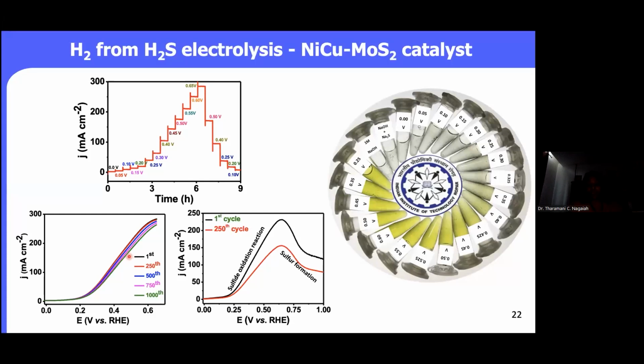To demonstrate whether restricting the potential will work or not, we have performed the experiments. That means we have polarized the sample beyond 0.6 volts. You can see that after 0.6 or 0.7 volts, there is a decay in the current. That means there is a production of sulfur directly during the electrocatalysis. It is accumulating on the electrode surface.